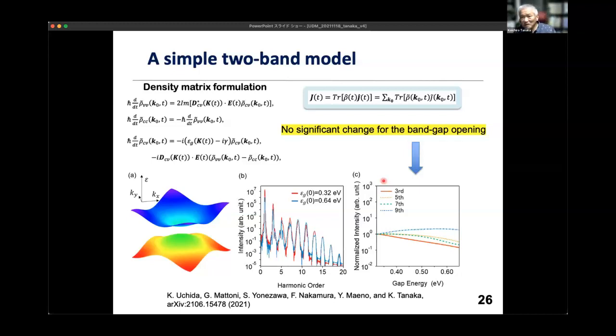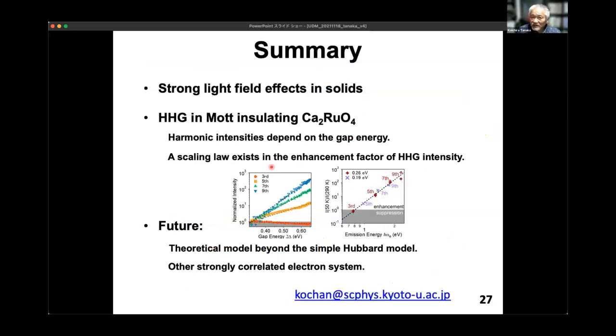All right, so time is up. I'd like to summarize my talk. We obtained a strong field effect in strongly correlated materials, and we observed high harmonic generation in Mott insulating calcium-2 ruthenate. We obtained very large enhancement at low temperatures and found a simple scaling law for emission energy and the gap energy. But at the moment, we do not have any theoretical explanation.